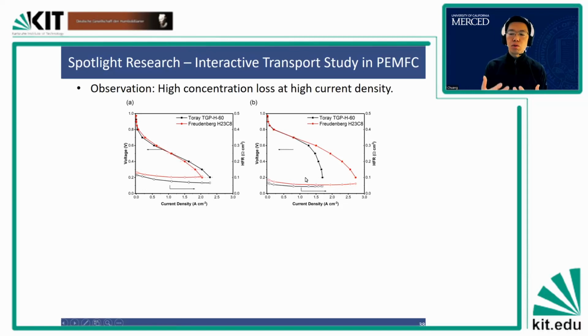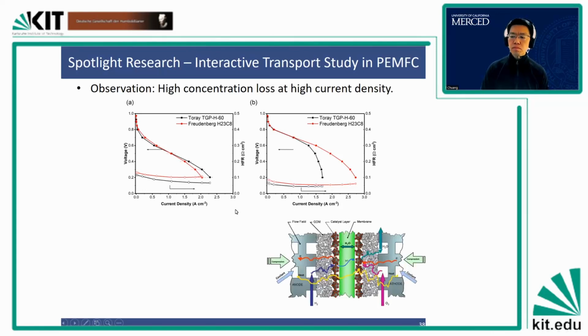We observe this problem, and we want to make the black one run as far out as possible. I showed you this feature before. This is the MEA in the middle, and these two materials, one is Toray, one is Freudenberg. This refers to the GDL, the transport layer here. I plotted this not to scale, because the MEA, the membrane and electrode, has an entire thickness of usually about 20 micron, very thin. But this gas diffusion layer is at least 10 times thicker, about 200 micron. So a lot of the transport issues actually happen inside the gas diffusion layer.